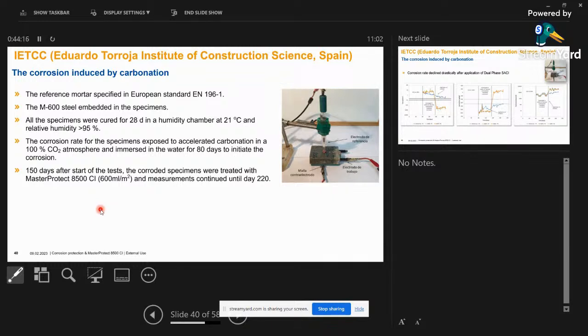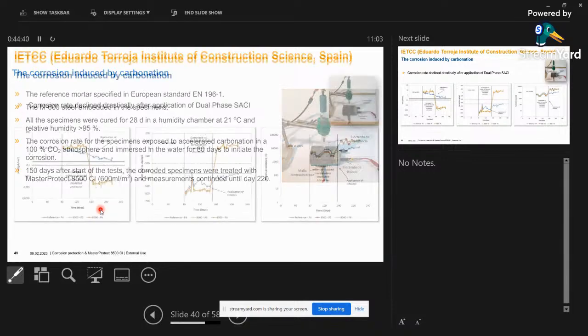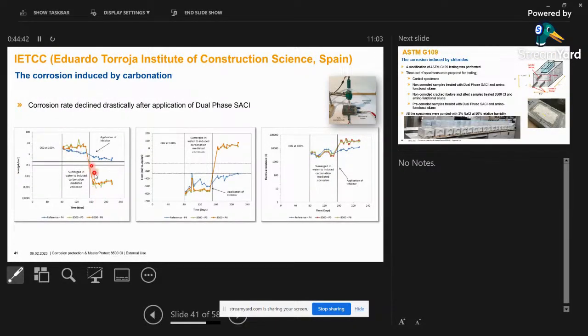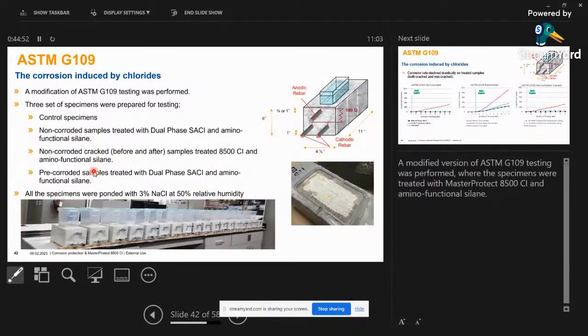And what it measures, it gives you an idea of the increase in the resistivity. It tells the potential starts to drop because it is effective in passivating the steel reinforcement as well. So you see that there is a drop in the electrochemical potential. There is a drop in the activity if you measure. So I'll show here that there were corrosion currents also which were measured, and it was found to be quite effective. And you see the corrosion activity going, and you see here it starts to drop after application of the inhibitor. So that's the kind of effect that it has in terms of resisting the corrosion activity.